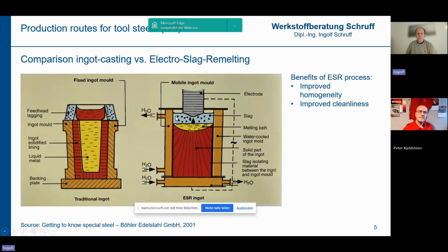This electrode is immersed with the lower end into an artificial slag. That is a substance with a given composition. I cannot exactly say what the constituents of this slag are, but it works like a filter in the process. It is heated up to approximately 1,700 degrees. And so we need to know that the electrode as well as the bottom plate here are connected to electric power supply. And due to the electric resistance, the steel of the electrode starts to melt into droplets, which then pass the layer of the artificial and liquid slag.